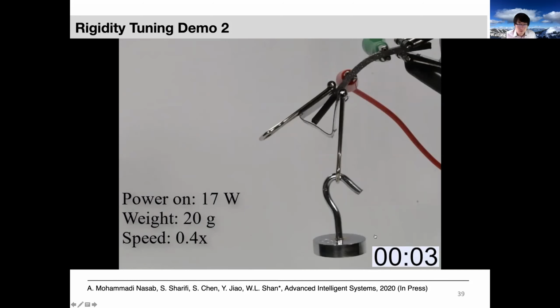Okay. Yeah, so this video demonstrates that this has much better properties than previous smart materials. It has tunable stiffness, roughly 20 to 30 times. But at the same time, its electrical conductivity can be tuned. And now we have evidence. We show that we can activate these samples using a lithium-ion battery with a few volts. This has never been demonstrated before.